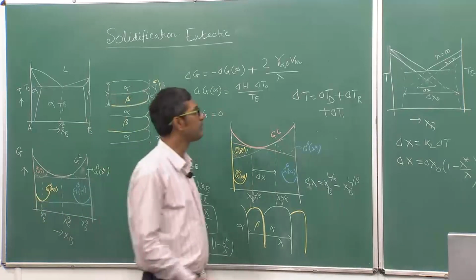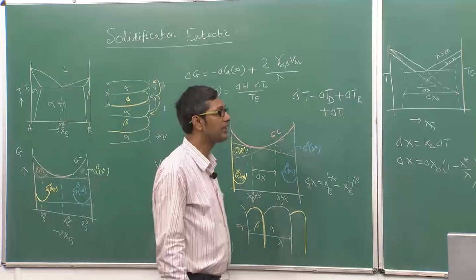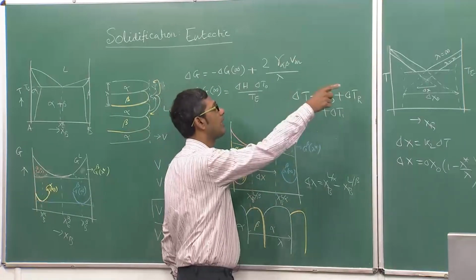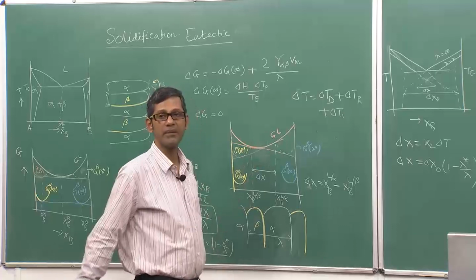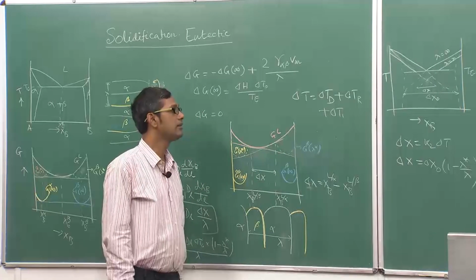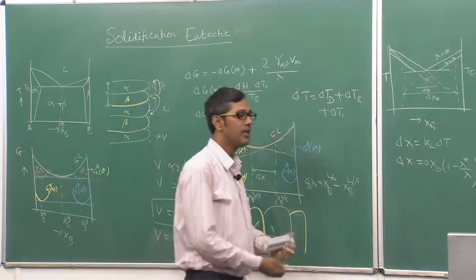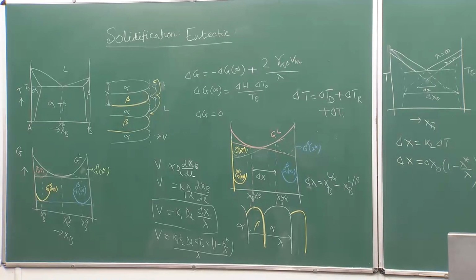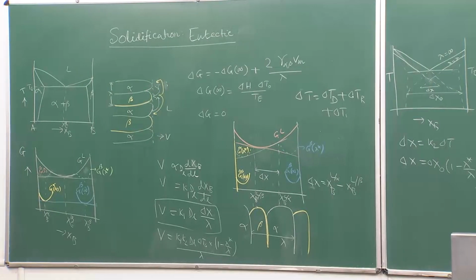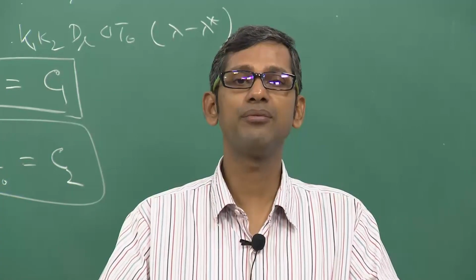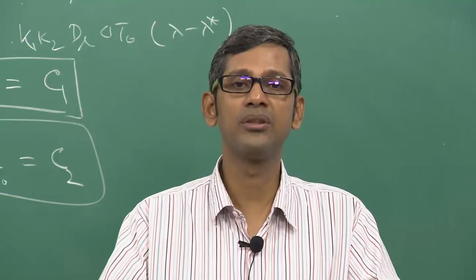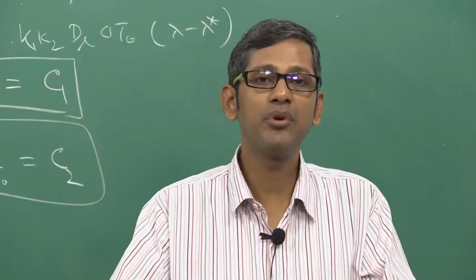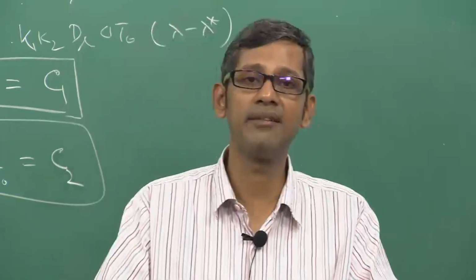In an actual experiment we cannot measure each of these; we can estimate them later theoretically. We can measure the total undercooling, plug it into the velocity versus lambda relationship, and get the velocity. So as you see, eutectic growth is much more complex than can be thought of. Compared to dendrites, eutectics are equally widely observed in microstructures, so it is important that we know their growth very well, but unfortunately those theories are still not developed.